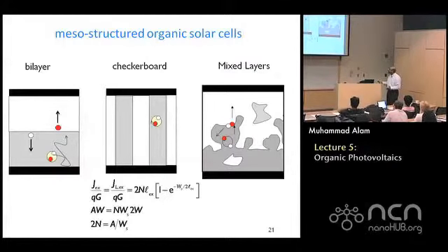Look at the area. This area was a planar area. In many of the gels and in other things, the area per centimeter cube, if you mix it very well, and each domain is a micron size, the area could be 2 football field size per centimeter cube volume. That is how big this surface area has become. Every exciton, essentially close to 100% of them, the light that came in, everybody will be dissociated. This is how efficient organic solar cells these days are. Exciton part, of course, we have to pull them, bring them out. That's the second question. But at least getting them dissociated, no problem.